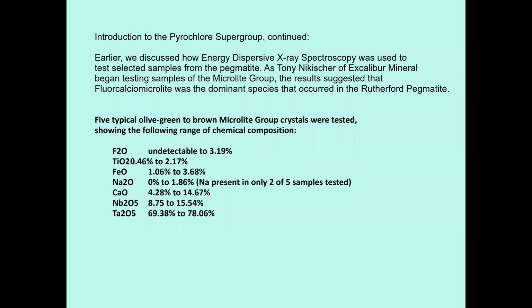This is continued in an introduction to the pyrochlore supergroup. Earlier, we discussed how energy dispersive X-ray spectroscopy was used to test selected samples from the pegmatite. As Tony Nikischer of Excalibur Mineral began testing samples of the microlite group, the results suggested that fluorcalciomicrolite was the dominant species that occurred in the Rutherford pegmatite. Five typical olive green to brown microlite group crystals were tested, showing the following range of chemical composition.